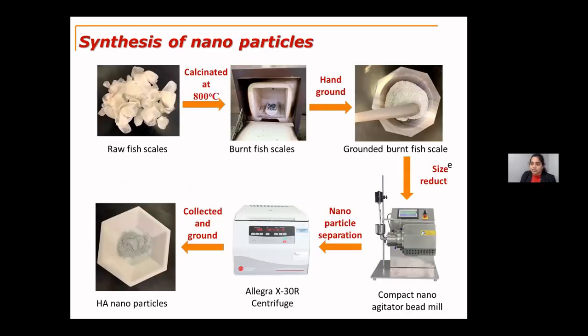First, let's discuss the synthesis of the nanoparticles from the bio waste. For the synthesis, we consider the fish scales of the Carp fish, in particular the Rohu and Katla fish species, which belong to the Carp family. They were sun-dried, and the moisture content is 70% before obtaining them. So these raw fish scales are calcinated, I mean, they are burnt in the box furnace at about 800 degrees centigrade for 3 hours.